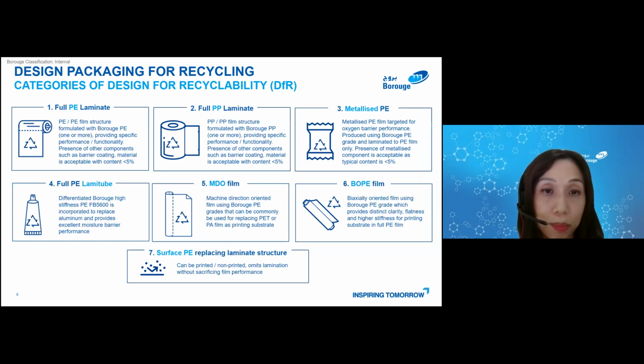From the top left, we have the full PE and PP laminate solutions, providing specific performance and functionality. And if required by the application, the presence of other components such as barrier coating material is acceptable with content of less than 5%. There is also oxygen barrier performance. If requiring oxygen barrier performance, we have the metallized full PE film solutions, and the presence of metallized component is acceptable for recycling as the typical content is also less than 5%.